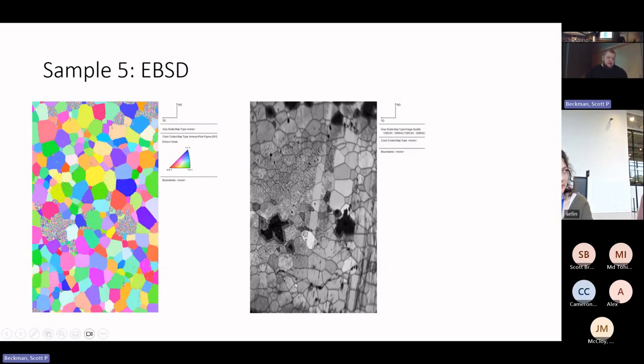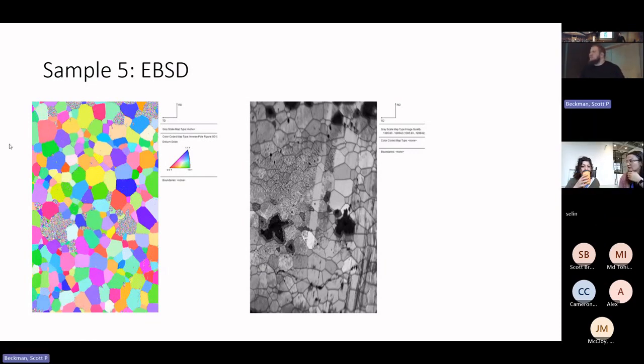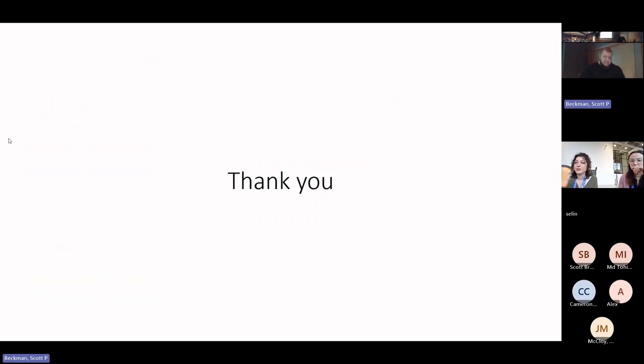We can see fairly regular grain structure, which is what we're looking for in our pellets. There's not as huge of a grain size distribution as you saw in some of the other pellets that we made, which I'm not going to talk about, made from cerium oxide and others that had very irregular grain structure. This grain structure is similar to what we'd expect to see from literature on highly transparent yttrium oxide samples, which tells us that as far as our grain sizing, we're on the right track. We just need to work more on the density of our samples and mostly on the impurities to get high optical transparency.